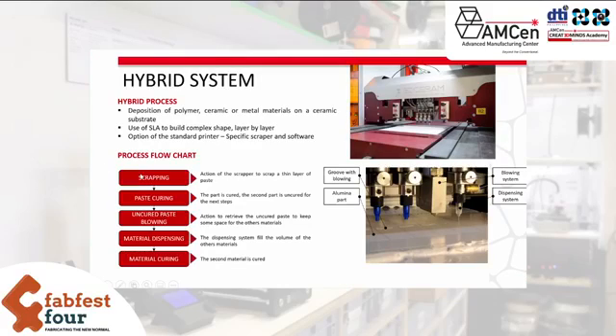First, we scrape the ceramic paste on the printing platform. So it is the same thing as for the standard process. Then we cure the ceramic paste only on the area where we need fully dense ceramic at the end. We scrape and we cure the ceramic paste. Then we blow the uncured paste with a specific nozzle in order to create a gap, a groove, on the area where we want to deposit another material. So we blow with compressed air.